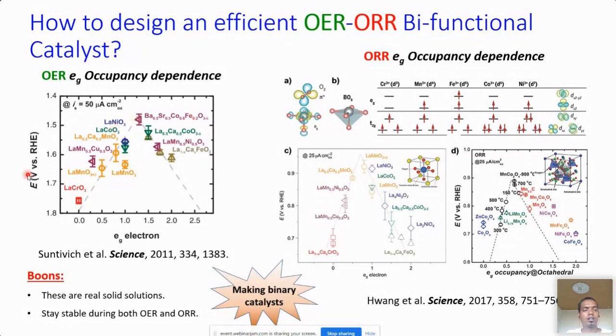So here we have EG electron correlation, as shown in the earlier slide, for ORR and OER. We know that OER catalysts which have EG electron occupancy from 1 to 1.5 are the best, and ORR catalysts which have EG electron occupancy from 0.5 to 1 are the best. So if you formulate a catalyst combining these two, having an EG electron occupancy of around 1, you could end up with the best bifunctional catalyst, which can be very helpful in realizing high specific capacity and high energy density in metal air batteries.